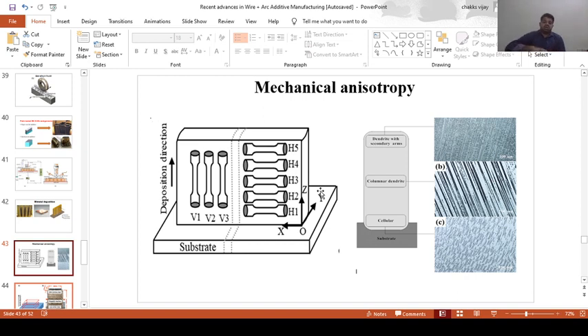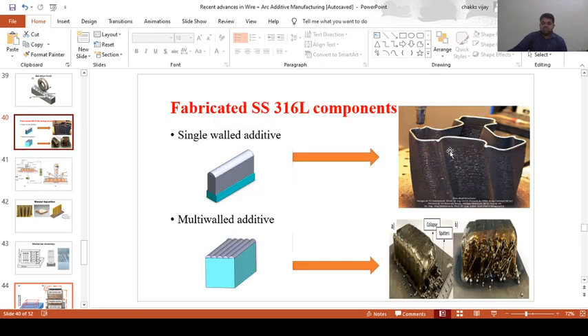But when we take a sample in the transverse direction, this is the transverse direction and this is the longitudinal direction, the tensile strength would be rather poor, but not too much. This is called mechanical anisotropy. Why does this mechanical anisotropy persist? Because whenever we deposit, this area will have one kind of grain morphology, this particular area will have another grain morphology, and the bottommost area will have a very different grain morphology.